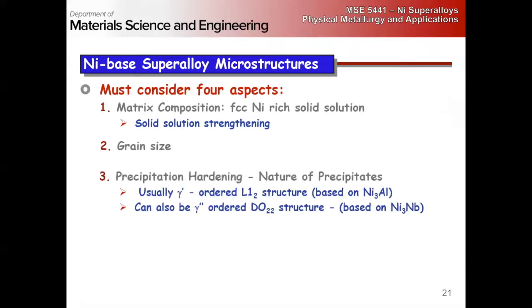We need to control grain size, right? Why is grain size something that we really need to consider? How does grain size play into high temperature creep life? Smaller grains are worse for creep, right? So in the limit of the blades, you go to a single crystal, no grain boundary area, essentially infinite grain size. It's going to be best for creep, right? But we also have a trade-off with fatigue, where large grains are going to be worse for fatigue.